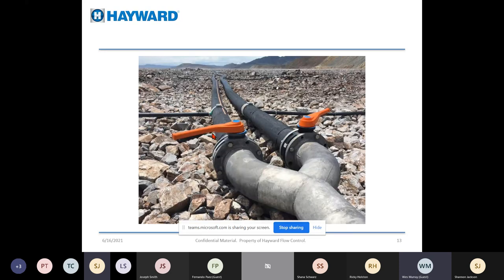This is a slide of a mining application. This is actually heap leach. In this application, this is crushed ore from a mine. They're extracting copper out of this crushed ore, and they do that by sprinkling sulfuric acid at, I think, a 3-5% concentration. So these are distribution lines for sulfuric acid. The acid's sprayed on the surface and it percolates down, and then there's a method of collecting this material, and then the copper ions are separated out of solution.